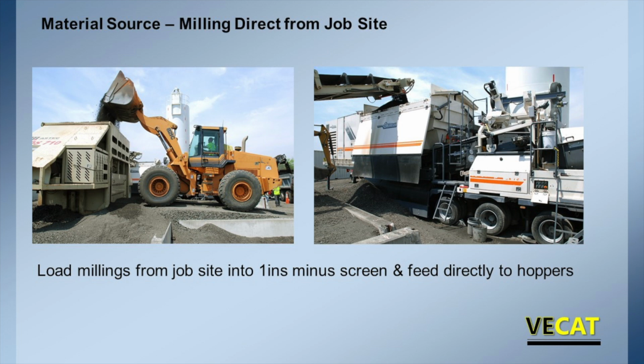Maybe you've got 5% oversize. But that's a 1-inch minus screen. Then we load directly into the plant. So we're controlling the gradation of the material we're going to recycle and mix. And that really is very, very important. If we're going to have chunks in a mix, we can't pave them, and we'll have weak spots in the base, and we'll get failures. So controlling the actual sizing of the material is really very, very important.